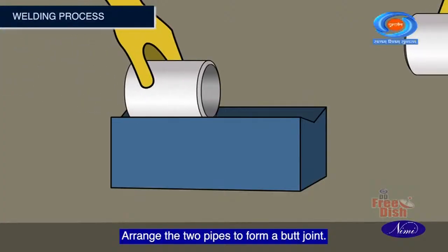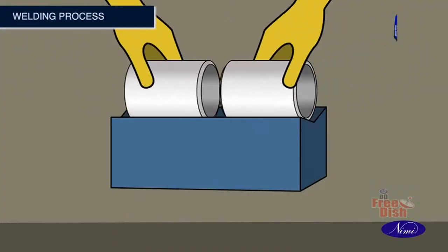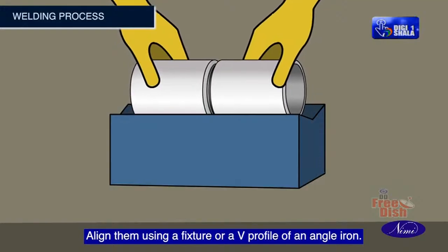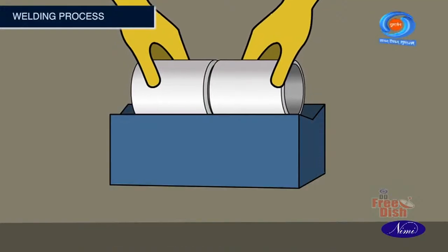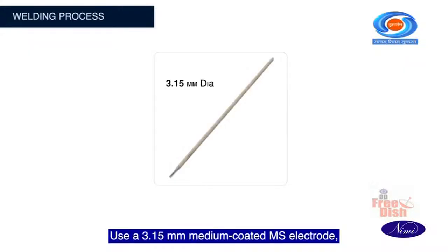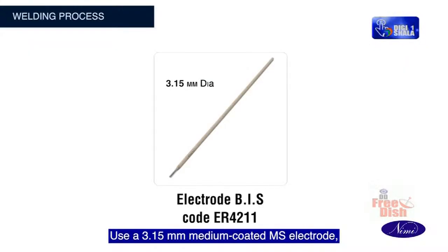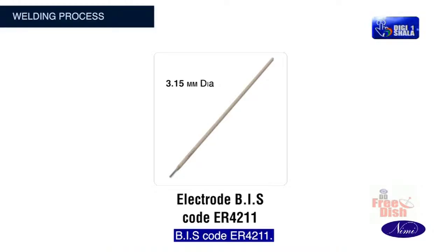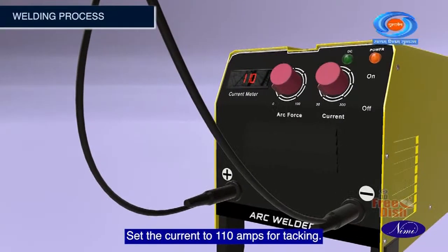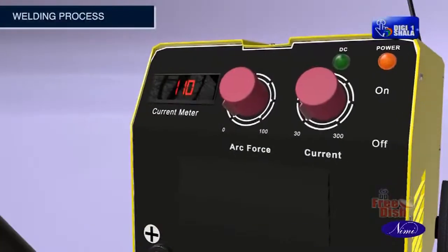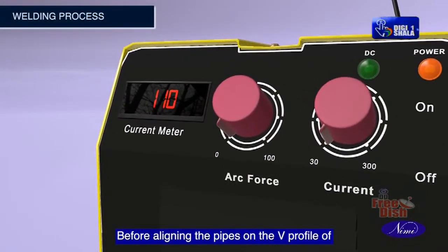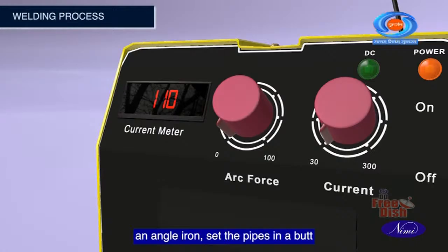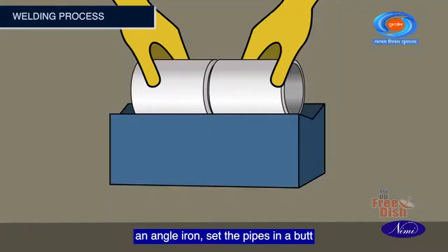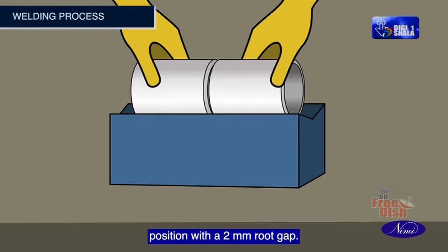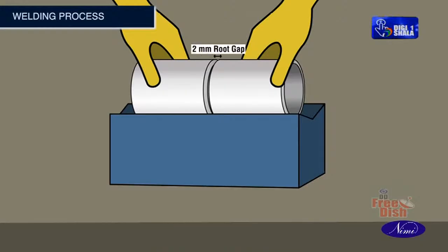Arrange the 2 pipes to form a butt joint. Align them using a fixture or a V profile of an angle iron. Use a 3.15 mm medium coated MS electrode, BIS code ER4211. Set the current to 110 amps for tacking. Before aligning the pipes on the V profile of an angle iron, set the pipes in a butt position with a 2 mm root gap.